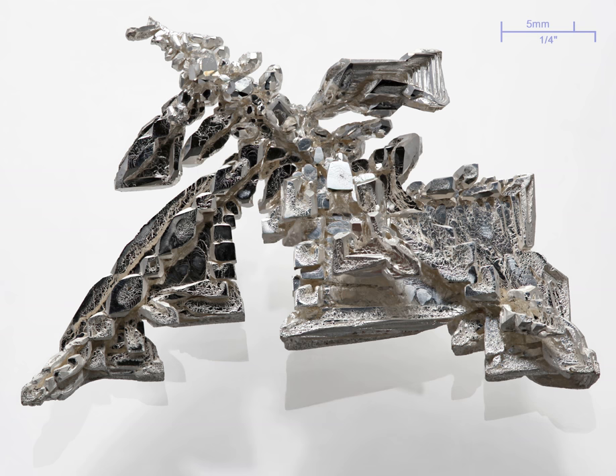Metallic silver, like copper, is an antibacterial agent, which was known to the ancients and first scientifically investigated and named the oligodynamic effect by Carl Nägeli. Silver ions damage the metabolism of bacteria even at such low concentrations as 0.01 to 0.1 mg per liter. Metallic silver has a similar effect due to the formation of silver oxide. This effect is lost in the presence of sulfur due to the extreme insolubility of silver sulfide.